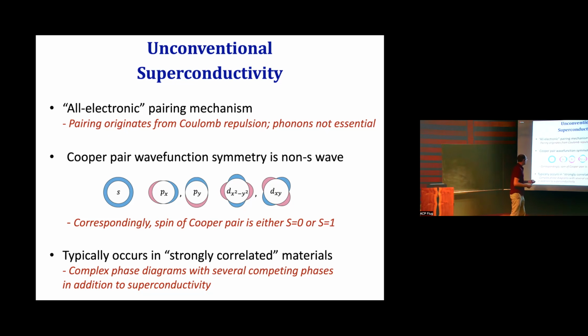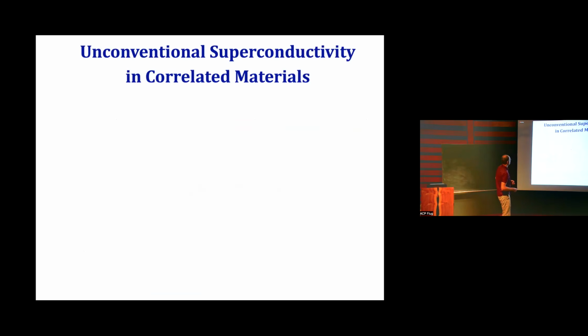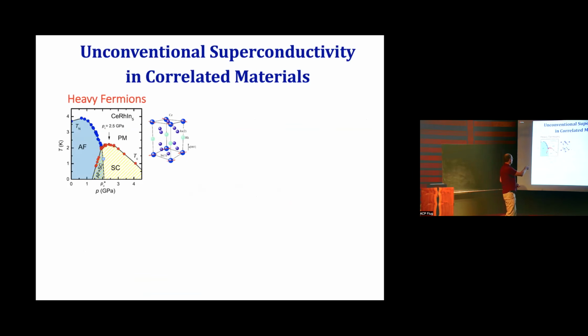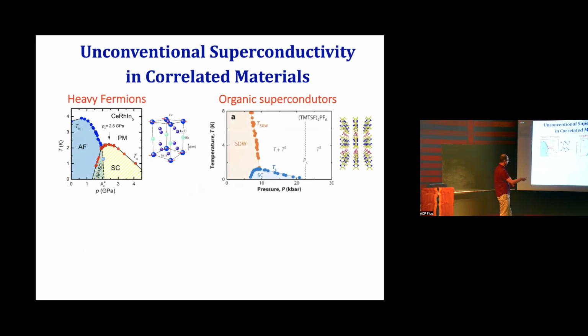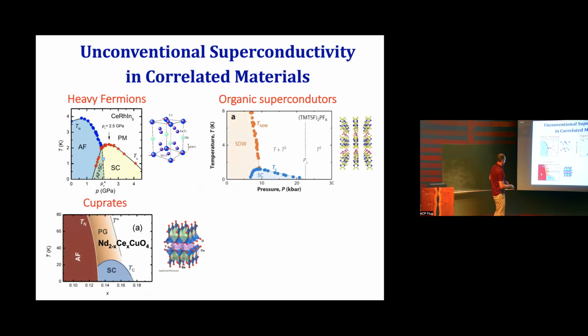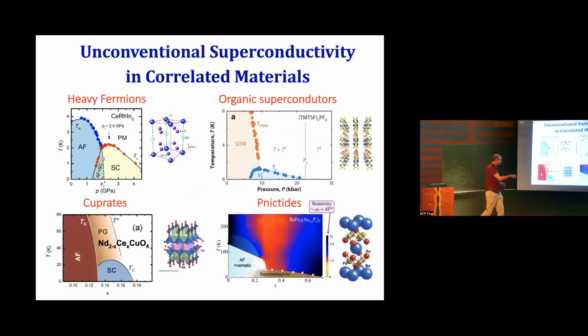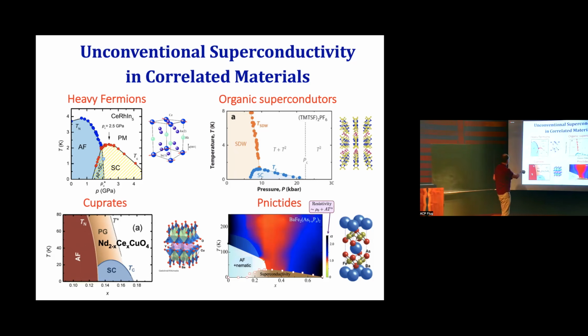Okay, so just to flash a few materials. These are so-called strongly correlated materials. This is a heavy fermion material, an organic superconductor, a cuprate superconductor, and an iron-based superconductor. These are the crystal structures, totally different chemically, totally different crystal structures. You see the phase diagram. Sometimes I'm plotting the phase diagram as a function of pressure and temperature, sometimes as a function of material composition and temperature. But nevertheless, you see the striking similarity in the overall shapes of these phase diagrams.